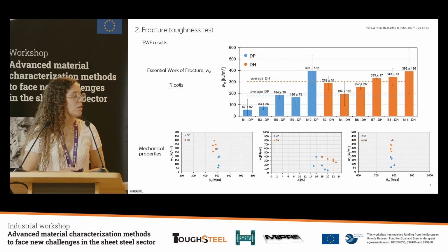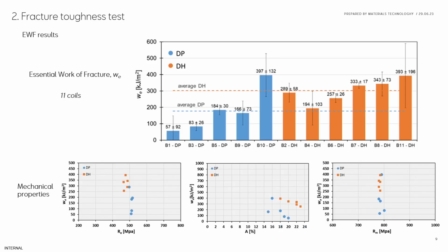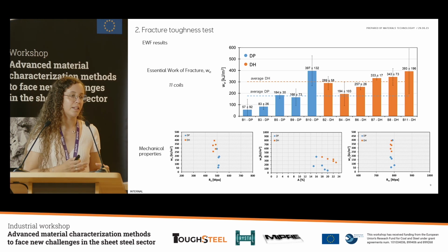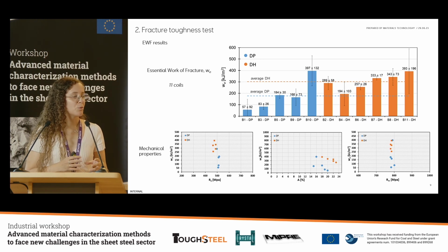So we got these 11 coils, and here we can find the results that we obtained for the essential work of fracture values. We separated here in blue the material DP, and in orange the results for material DH. And we already saw a tendency with better results for the material DH. So we already knew with this parameter that this material would be better than the DP for edge cracking or cracking problems. Also, what we could find is that some DPs had good fracture toughness values, so maybe these ones could be used to fabricate the pieces without any cracking problems, and it would be a good way to choose between the DP materials the best ones to use in the process.